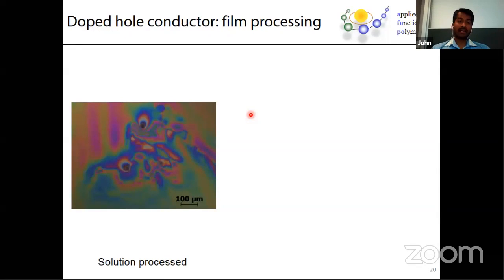And what next? We found that we can actually dope spiro, but is it of any use? Whether the system can find any applications or has any technological relevance. In all technological applications, we need to prepare films. Unfortunately, the system that we prepared, spiro-MeOTAD and copper TFSI, was not producing neat films. In order to go for a device or an application, the first important parameter is to have a clean, uniform film without any holes or any aggregation on the surface of the substrate. But it was not the case.